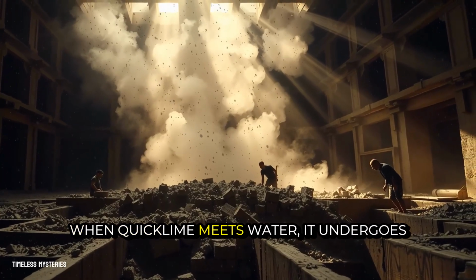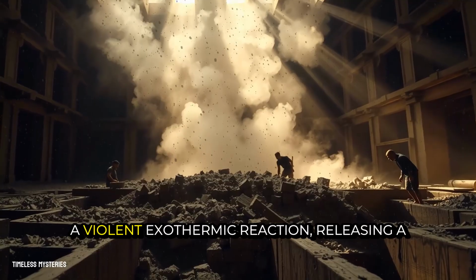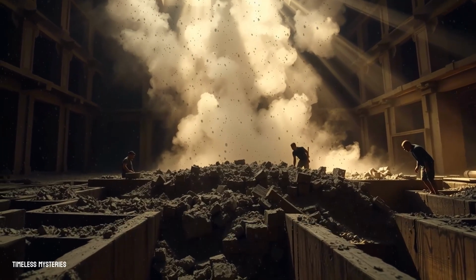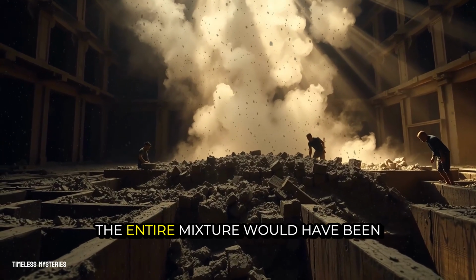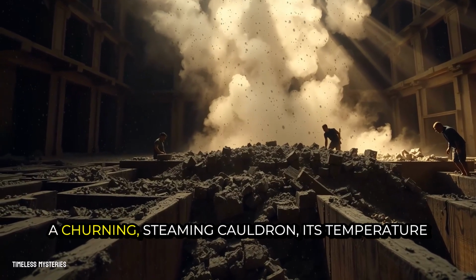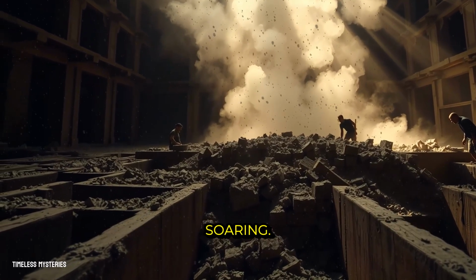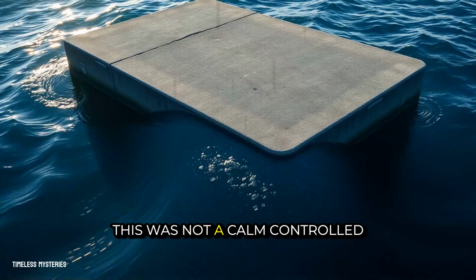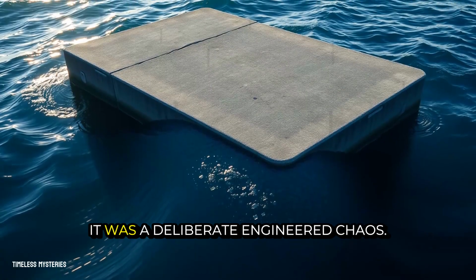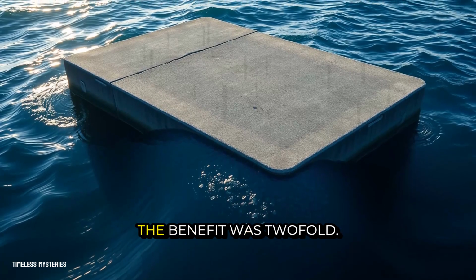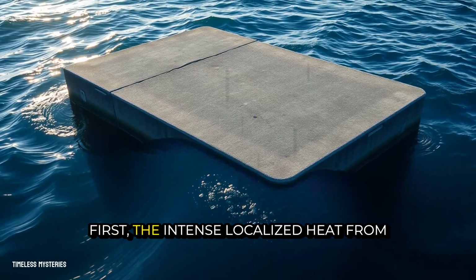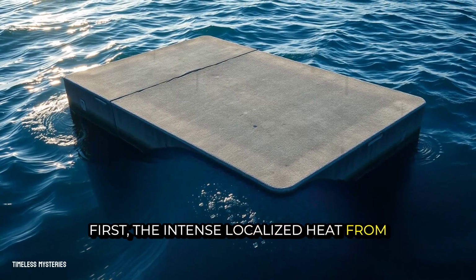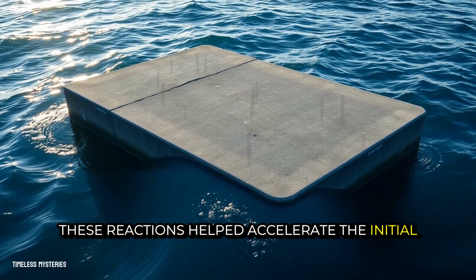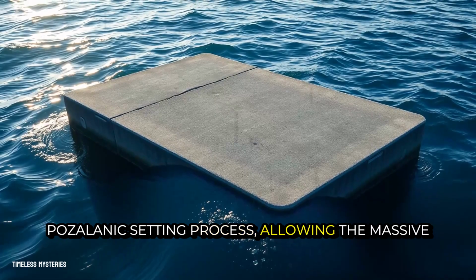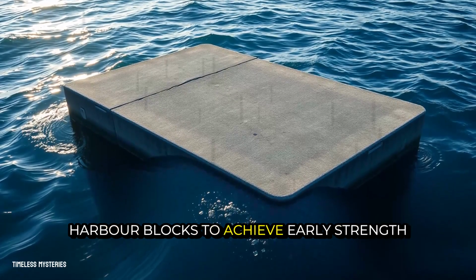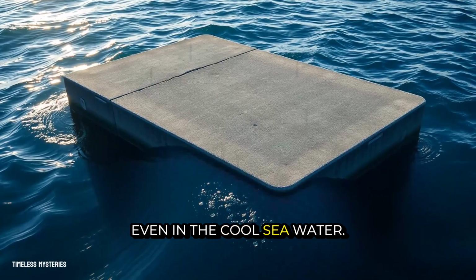When quicklime meets water, it undergoes a violent exothermic reaction, releasing a tremendous amount of heat. The entire mixture would have been a churning, steaming cauldron, its temperature soaring. This was not a calm, controlled process. It was a deliberate, engineered chaos. The benefit was twofold. First, the intense, localized heat from these reactions helped accelerate the initial pozzolanic setting process, allowing the massive harbor blocks to achieve early strength even in the cool seawater.